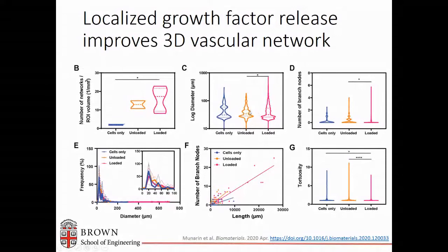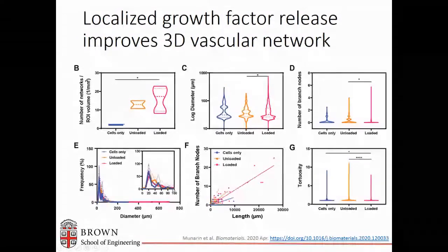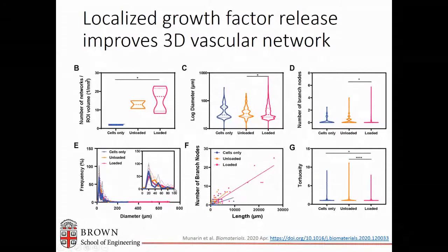The distribution of diameters of the vessels was not very different between groups at below 100 microns, but we did have some larger diameter vessels in the growth factor loaded group, and the number of branch nodes did proportionally increase and was no different between the groups with the increased length that we saw when we had loaded microspheres.